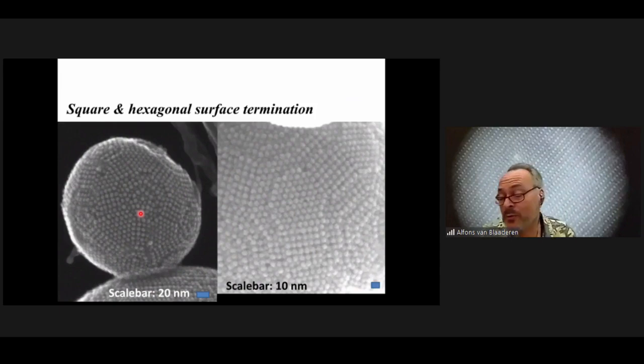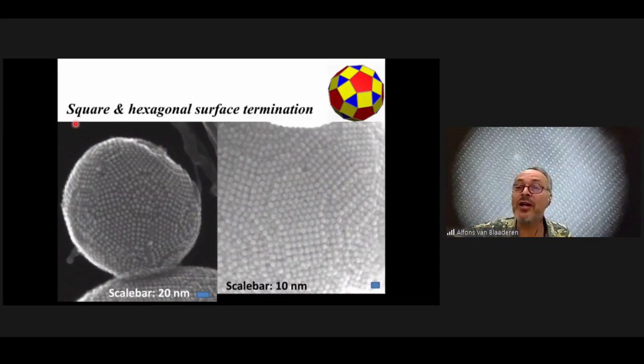So what we found is these beautiful five-fold symmetric structures. If you're not used to looking at it, here in the core is the five-fold symmetry. And now that we are used to looking at it, we actually immediately recognize, oh, this is a rhombicosidodecahedral surface-terminated structure. So that is one of the surface-cut icosahedral structures that you can get if you try to fit them in a sphere.